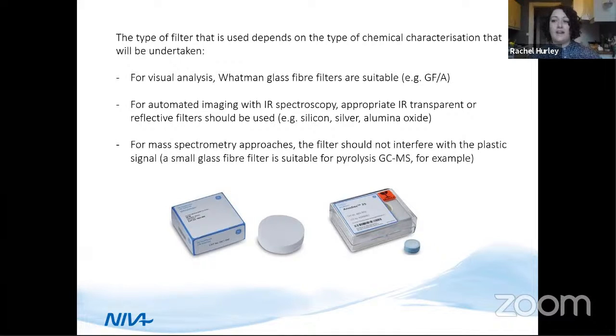If you're planning to use a more advanced or automated approach, such as using FTIR imaging, you should ensure to select an appropriate IR transparent or IR reflective filter. Some examples of suitable filter materials include silicon, silver, or aluminum oxide. This analytical technique facilitates detection of very small particles, so we can go down to around 10 micron with this technique. And so the pore size of these filters should also be correspondingly small.